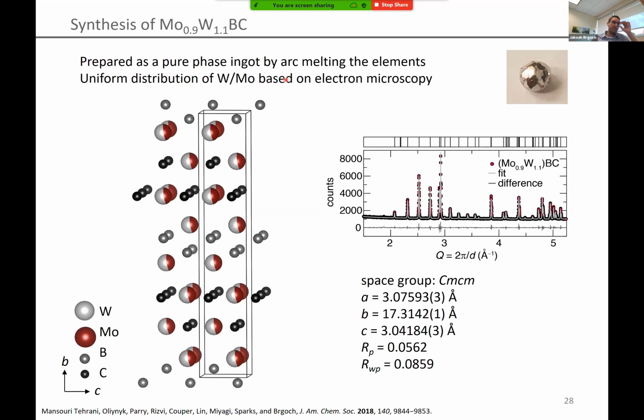Arc melting is basically taking a jar, purging all oxygen out, backfilling it with argon, and then striking an electric current through the argon, which creates an argon plasma. You can really easily achieve temperatures of 2,500 to 3,000 degrees Celsius quickly.